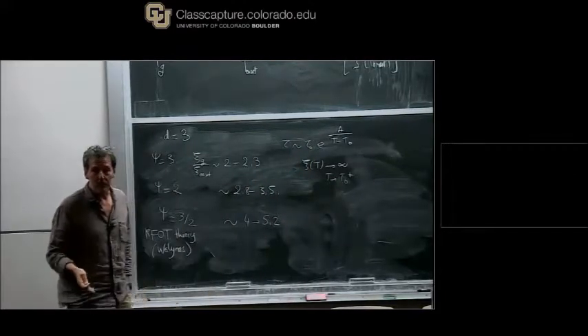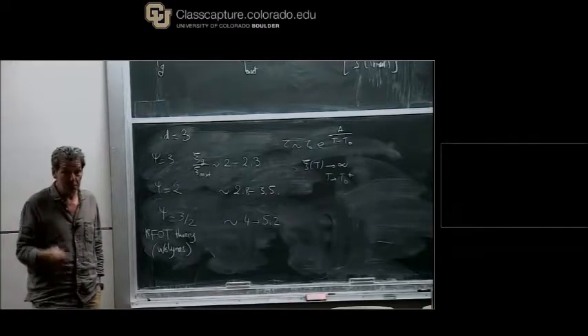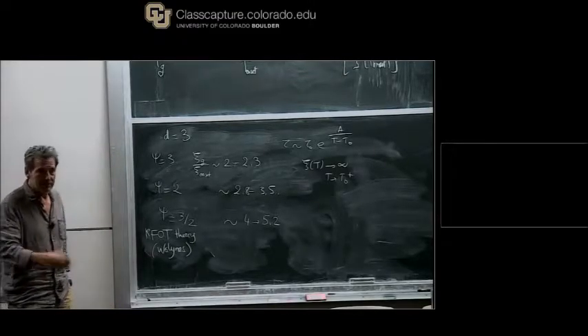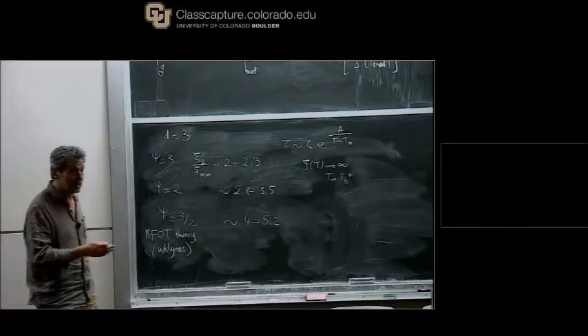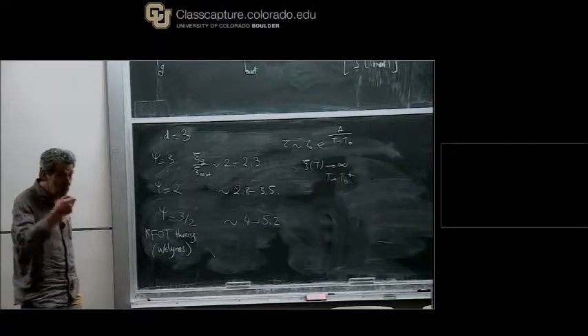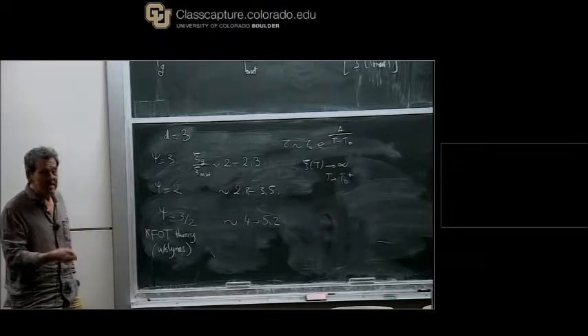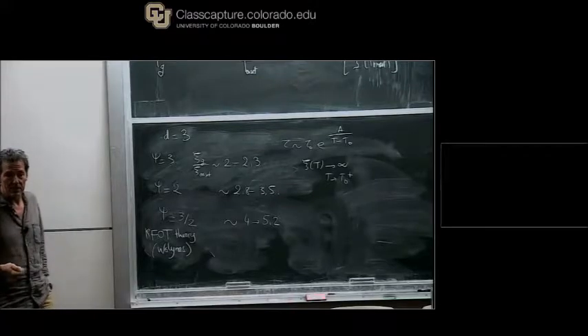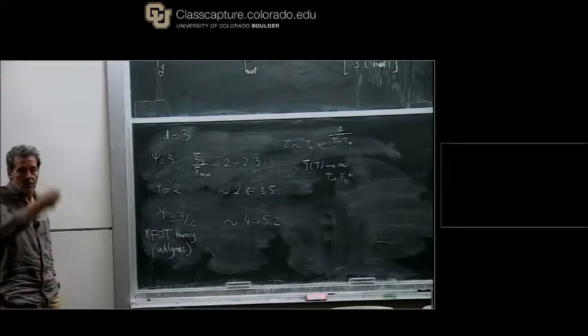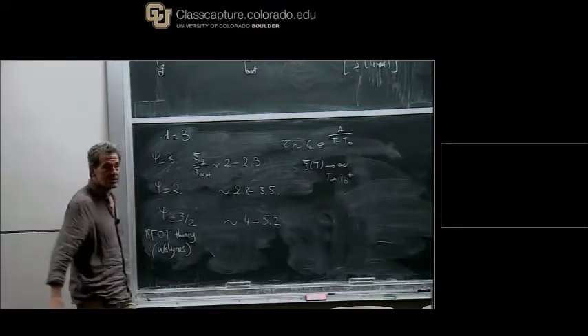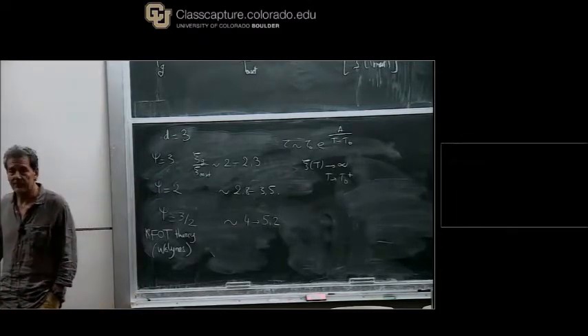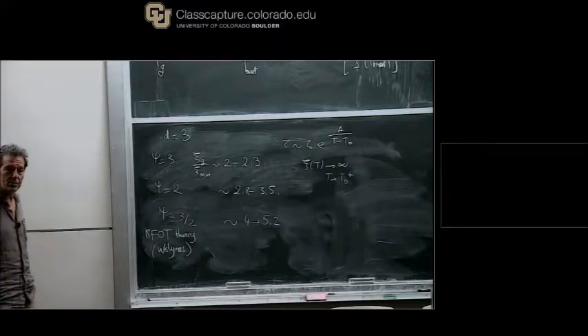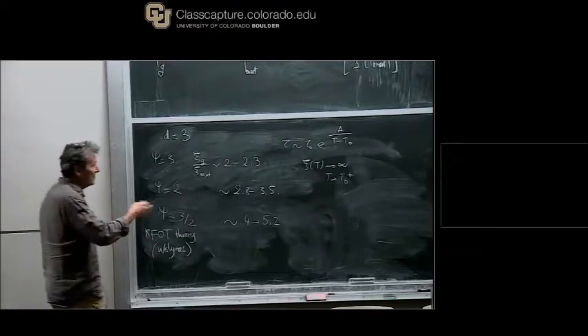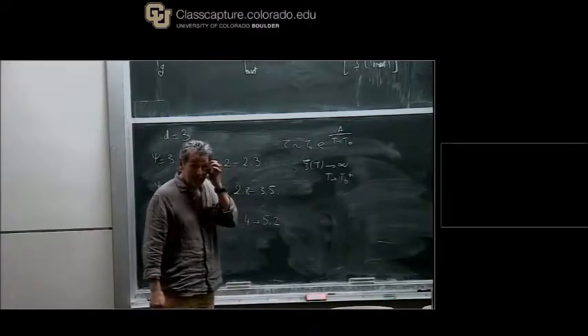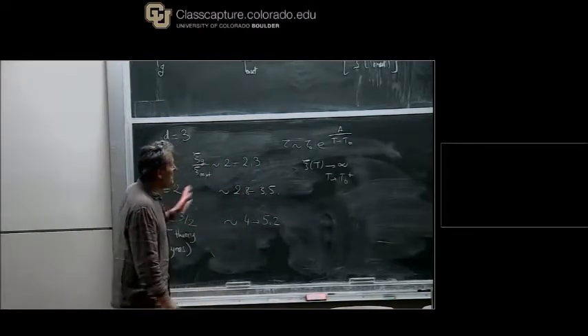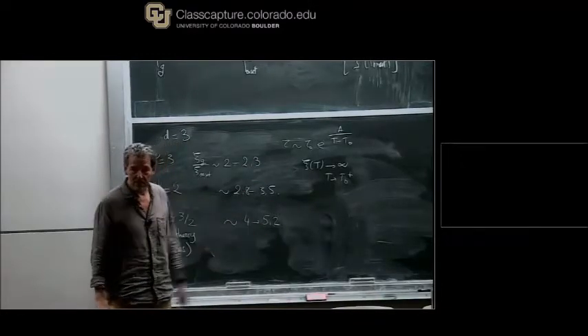So even if you have a critical point, and it's the same in systems where we can do real theory, in terms of predictions and all, like the random field Ising model, it's exactly what occurs. We know we have a critical point in that case, but even in experiment, it's very hard to get close to it, just because the relaxation times become so huge when the correlation length has increased by just a factor of 5. So you might gain a little bit with experiments, but it will always be very hard to probe the asymptotic behavior.